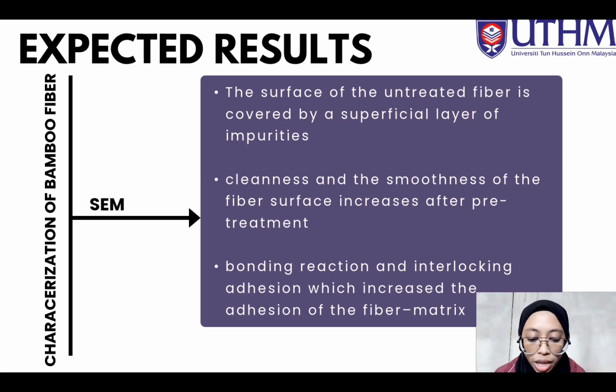We use SEM to know the cleanness and the smoothness of the fiber surface, whether it increases or decreases after pre-treatment. So we will compare the untreated bamboo fiber surface and the treated bamboo fiber surface. The surface of the untreated fiber is covered by a superficial layer of impurities, and the cleanness and smoothness of the fiber surface will increase after the pre-treatment. As a result, bonding reaction and interlocking adhesion increase the adhesion of the fiber matrix.